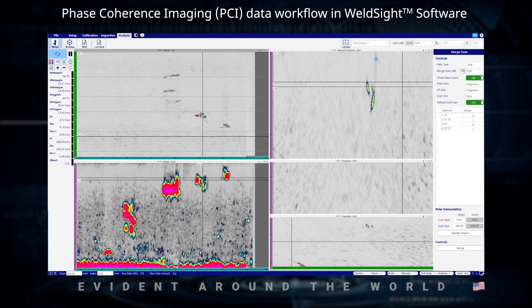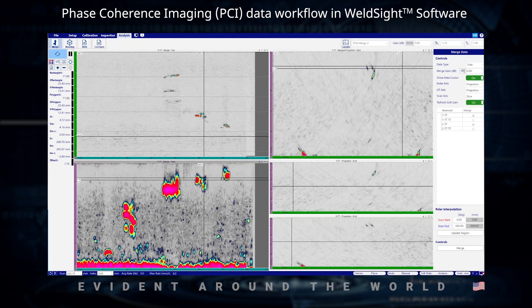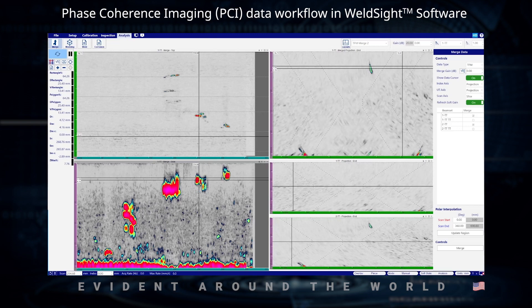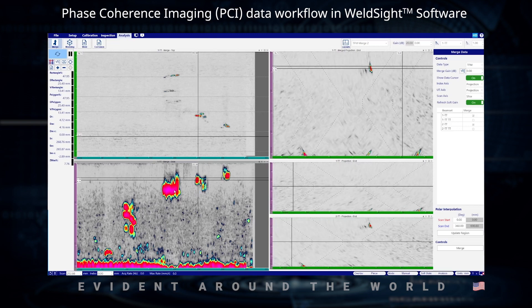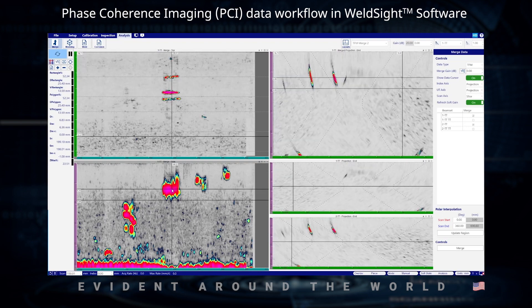I'm going to pull up another display here. Adding in the two unmerged groups as well kind of helps us see what's going on — see those individual pores from different sides of the weld and how they really pop out. It also helps us determine whether something's a planar flaw, really catching it with a lot of amplitude on our 270 skew versus on our 90 skew.